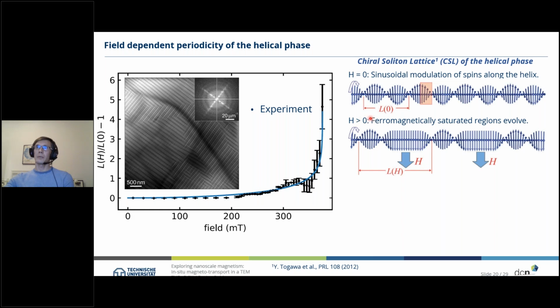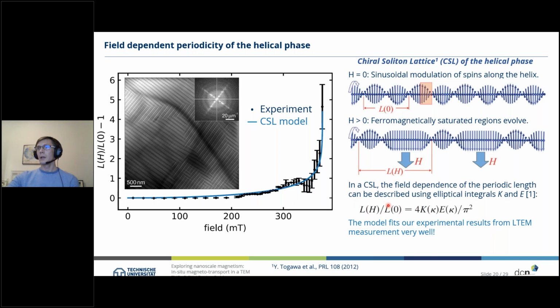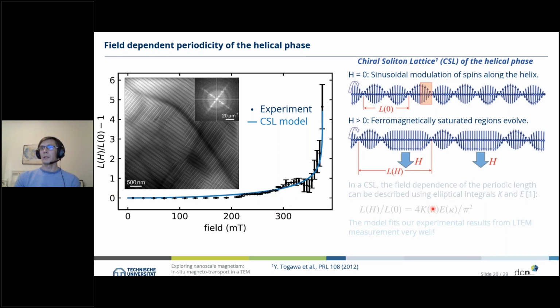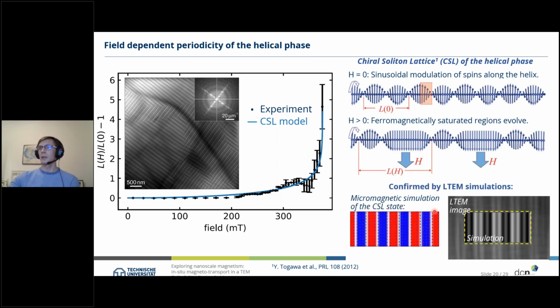If we apply the magnetic field, of course, one domain, one direction will be favored, as I described in the beginning, and we will have the growth of one region, and therefore an increase of the periodicity of these stripe patterns. This can be described by the chiral-soliton lattice model, which uses elliptical integrals of the first and second order, shown here on the bottom. If we use that equation and fit it to our experimental data, it fits quite well. We can then also do the micromagnetic simulation, and the Lorentz TEM images and the simulation fit quite well to each other. So that quite well describes our material.